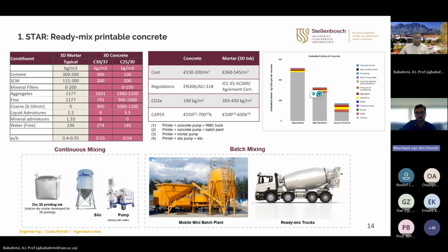So if we look at some typical 3D printable concrete mixtures, comparing a mortar to a concrete, for example, the C25/30 material, we're able to substantially reduce the cement content as well as the cementitious or supplementary material content. We incorporate a lot more aggregates, and in some of my next slides, I'll show you what the significance of this is, particularly related to the amount of paste required to coat those aggregates and the shrinkage performance of that material.